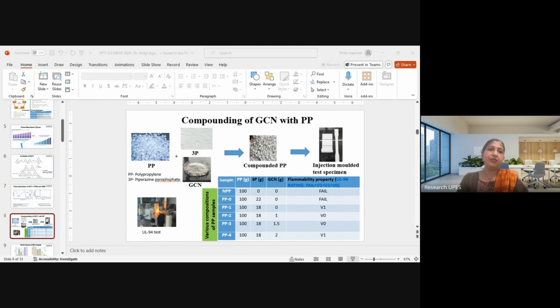Then this GCN we mixed with the polypropylene along with piperazine pyrophosphate. This piperazine pyrophosphate is used as a conventional flame retardant. But since it is used in high amount, we wanted to use some synergist so as to reduce its concentration in polypropylene. So we compounded it with the help of the extruder, and with the help of injection molding, we converted it into the specimen, which was tested.